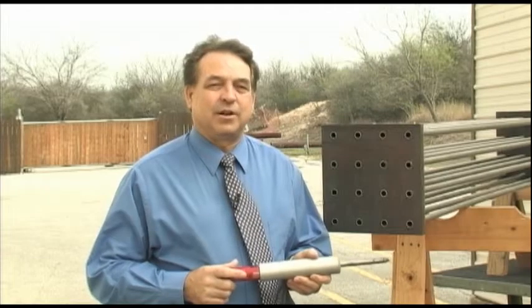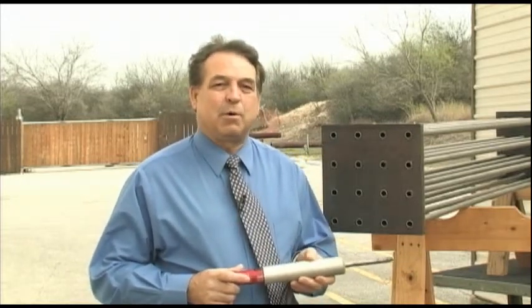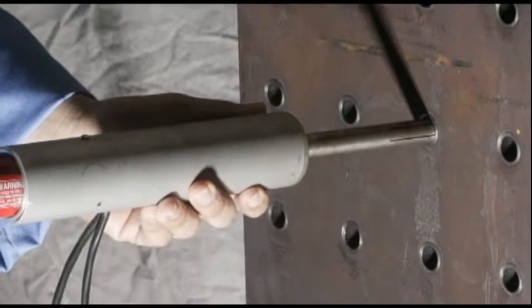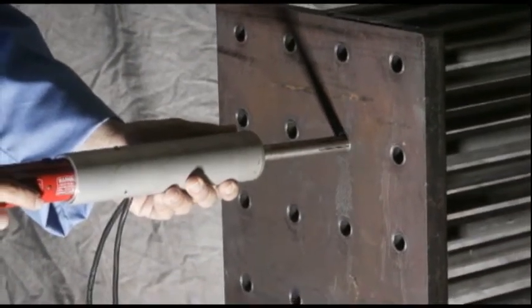Using the magnetostrictive sensor heat exchanger probe will allow the heat exchangers to be inspected with minimal preparation and save the industry time and money. This process allows us to inspect 100% of the tubes so that we don't miss any defects in any of the tubes, which provides a safer operating environment for the industry.